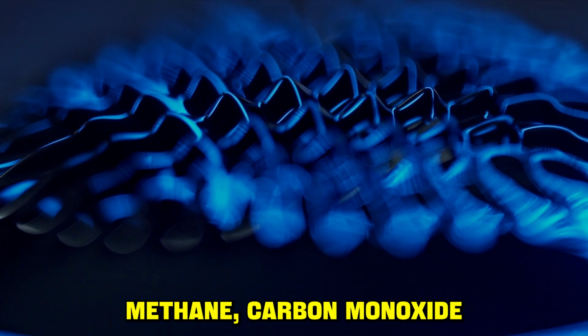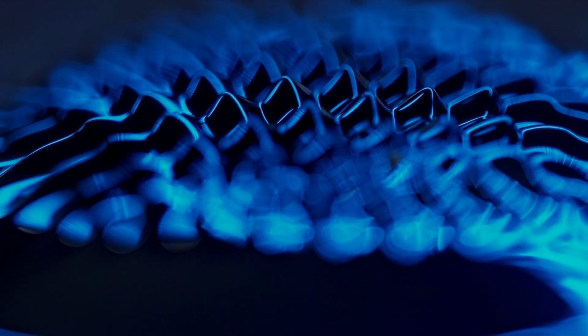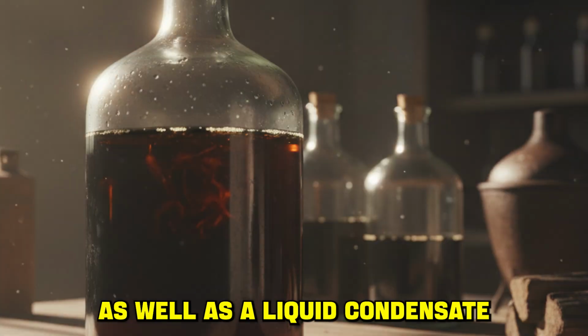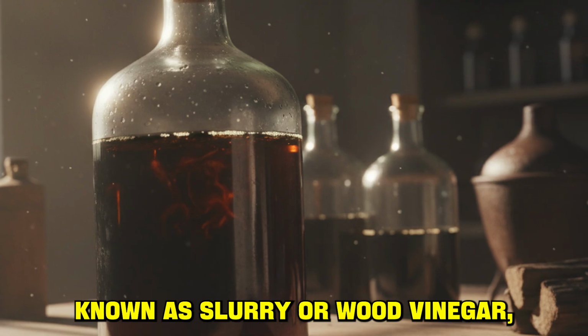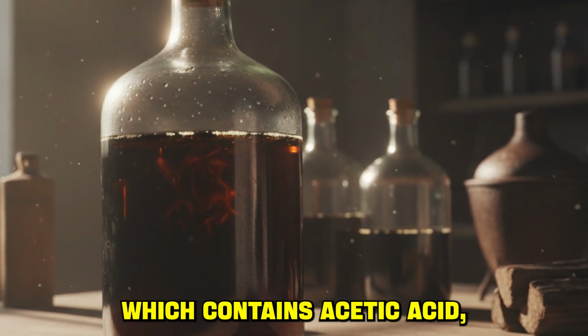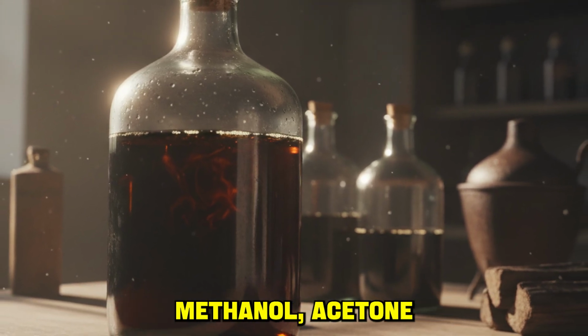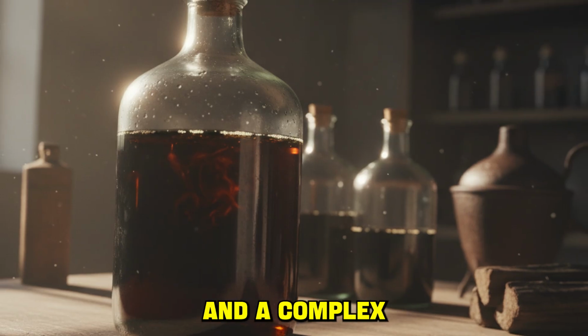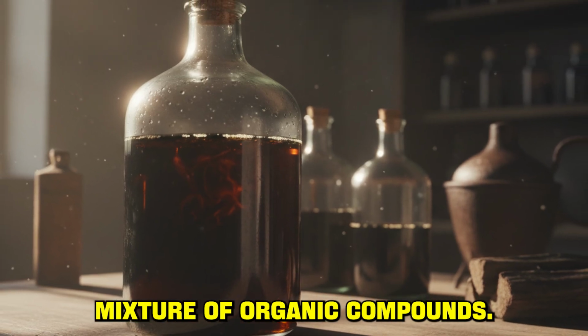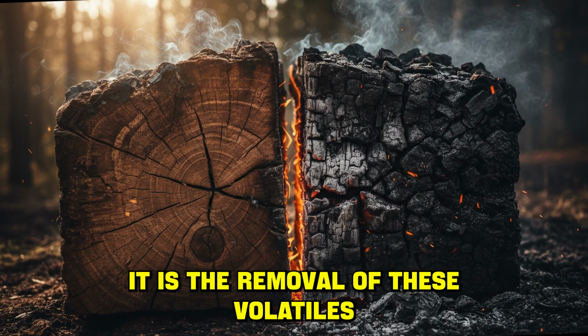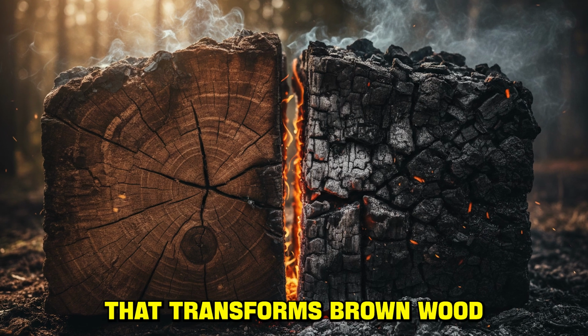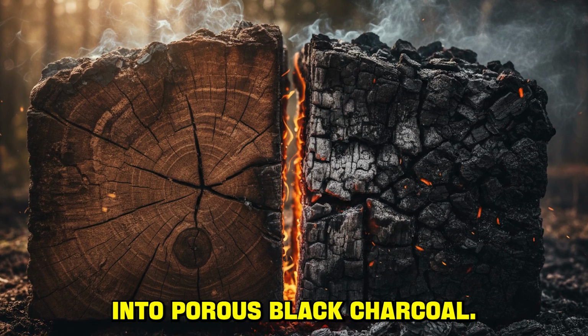Pyrolysis gases, consisting of hydrogen, methane, carbon monoxide, and other hydrocarbons, as well as a liquid condensate known as tar, or wood vinegar, which contains acetic acid, methanol, acetone, and a complex mixture of organic compounds. It is the removal of these volatiles that transforms brown wood into porous black charcoal.